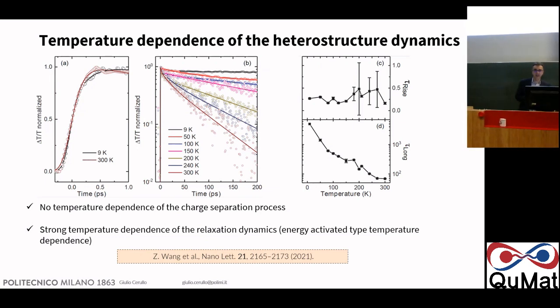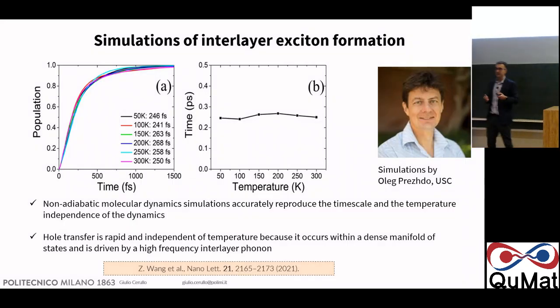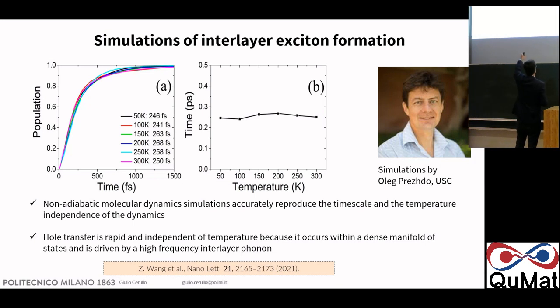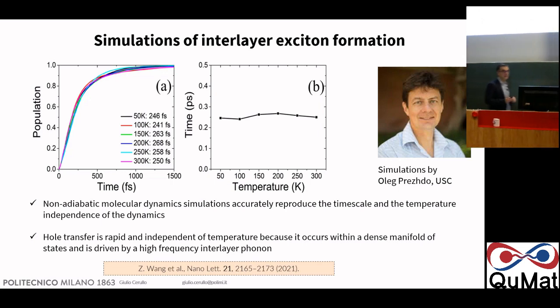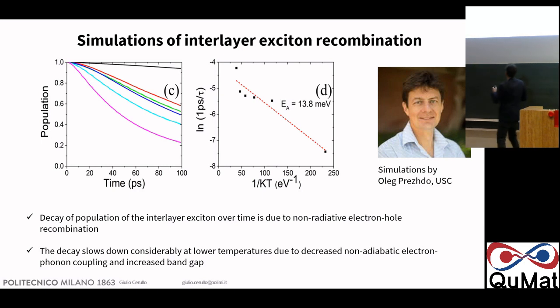So again, to understand these results, we asked the help of Oleg Prezhdo at the University of Southern California, who did non-adiabatic molecular dynamics simulation, and he could actually accurately reproduce the time scale of our dynamics. So he could reproduce that the interlayer hole transfer happens in approximately 250 femtoseconds, and it is nearly temperature independent. This temperature independence is explained by the fact that it occurs within a dense manifold of states and is driven by a high frequency interlayer phonon. And it can also reproduce the interlayer exciton recombination, which has a strong temperature dependence. The slowdown at low temperature is due to decreased non-adiabatic electron-phonon coupling and increased bandgap.